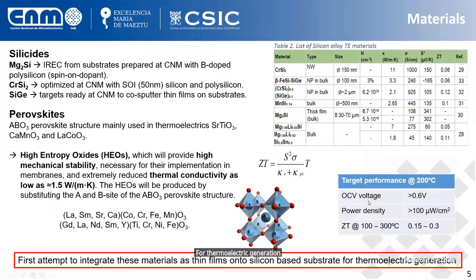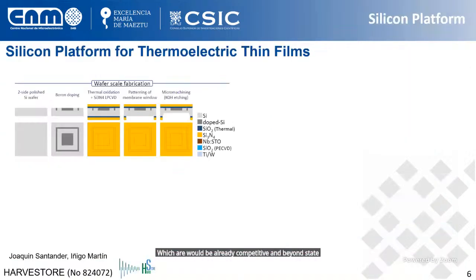The objective is to obtain open circuit voltages of 0.6 volts, power densities larger than 100 microwatts per centimeter square, and ZT figures of merit in this temperature range around 0.15 or 0.3, which would be already competitive and beyond state of the art.